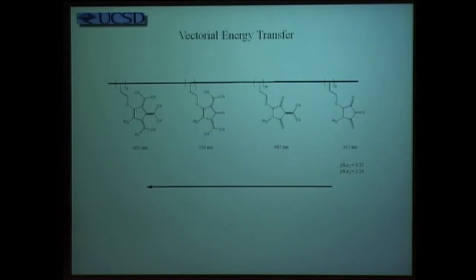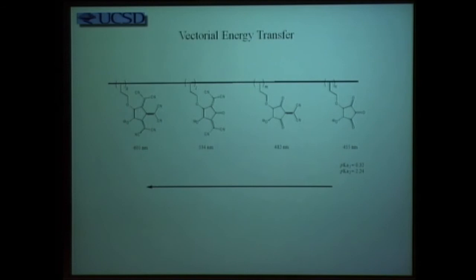And what that does is every time an oxygen is replaced by this CN2 group, what you'll find is that there's an absorption shift in each one of their maximum. So although each one of these would not absorb the whole of the solar spectrum, the whole aggregate, this polymeric species that has variable numbers of groups attached to a significant backbone would allow you to transfer only in one direction, from the high energy field, 415 nanometers, to the low one. So energy will migrate along this facet.